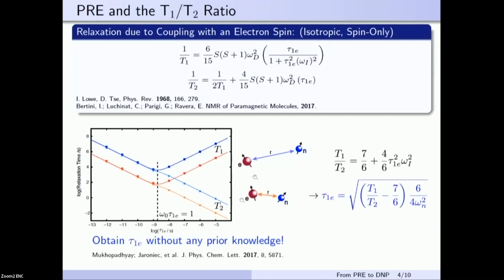And this can be shown mathematically just by dividing one equation over the other, and here we obtain that, in fact, T1e is proportional to the ratio of T1 over T2, and the only other unknown parameter is the Larmor frequency, which is actually a known parameter. So with this tool in hand, we went back to the manganese series and re-evaluated our results.